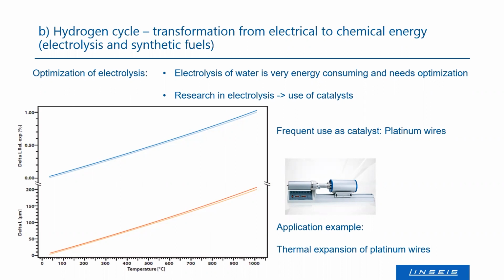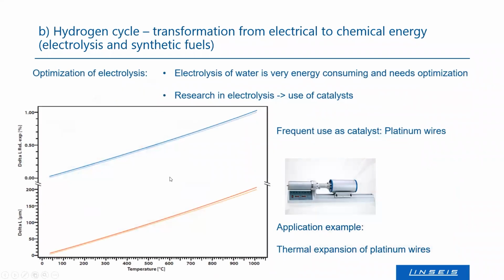In that case, it's a quite simple measurement of one of these electrodes. It's just an expansion measurement to get the coefficient of thermal expansion and the relative expansion over a decent temperature range, to be sure that if the material is getting hot, it is not expanding too much, or to know how much it will expand, to be able to properly build your machine. So that's where we are already also involved, more or less.